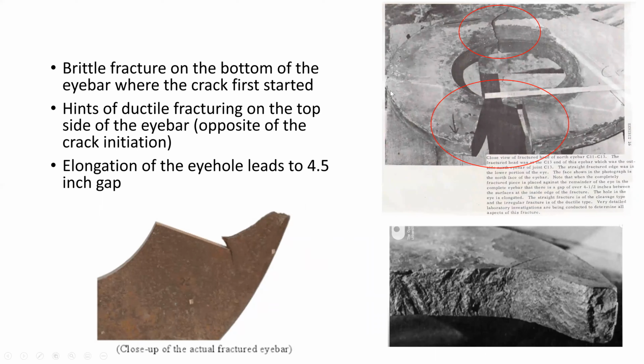The crack eventually made its way to the outer edge of the eyebar, resulting in a brittle fracture on the side where the crack first started, as indicated by the smooth break in the picture, and hence some ductile fracturing on the opposite side, as indicated by the jagged edge in the picture.